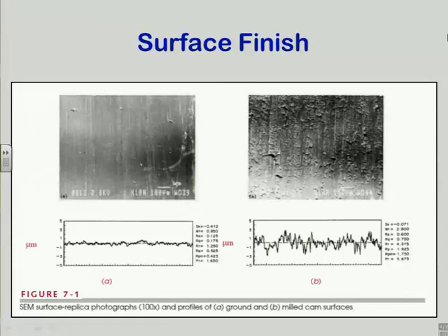And that's very slowly dragged across the surface. Not very far. That whole track is 2.5 millimeters, which is adjustable on this machine. And it takes 8,000 data points in 2.5 millimeters. So it's a pretty fine measurement. And that stylus, much like your record cartridge, is spring-loaded with a very light spring, so it's just riding over the surface. And the ups and down motions are being captured electrically and displayed here.